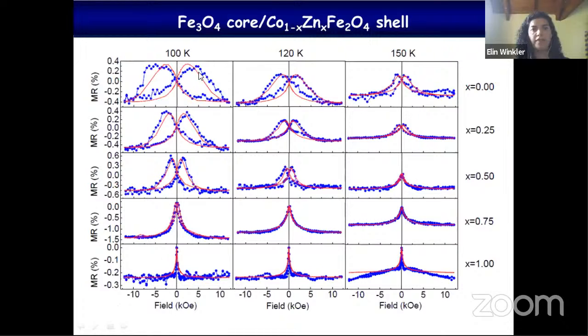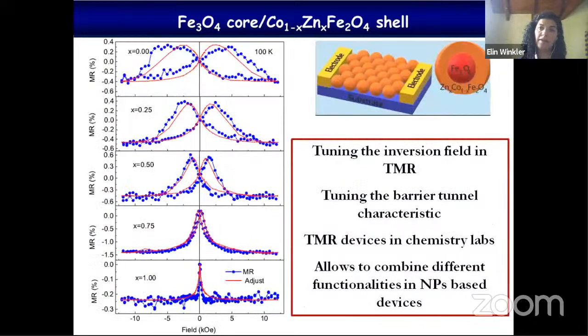when the cobalt of the shell is replaced, we can systematically reduce the maximum of the magnetoresistance. So we can tune these two resistance states of the system. The conclusion of this part is that the core-shell system allows tuning the inversion of the tunnel magnetoresistance, and we can also tune the characteristics of the tunnel barrier, and these devices can be fabricated in a chemistry lab, which does not require very expensive equipment and clean rooms.